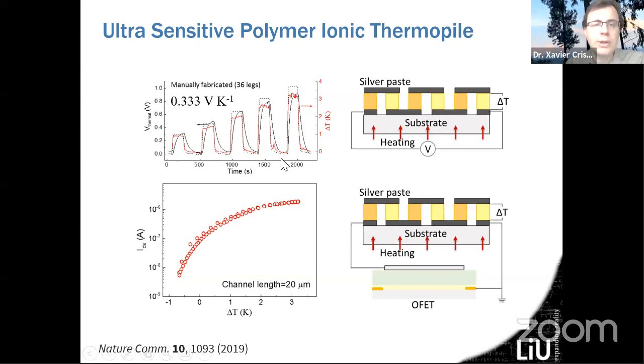So here, for instance, with 36 legs of positive and negative ionic Seebeck coefficient polymer, we get basically a very strong signal. When you apply a small temperature gradient, you get a huge voltage, basically something like 0.3 volt per Kelvin. So it becomes a very sensitive material and device for reading temperature gradients.